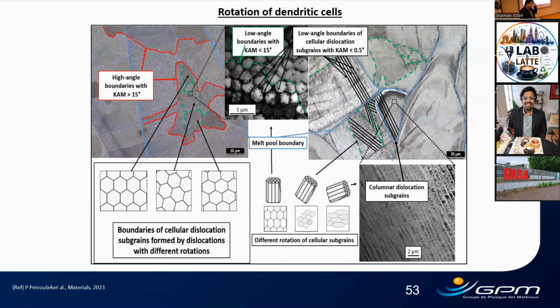So you spoke about microstructure. We did not speak much about defects. Just considering the large range, usually when you look at a range of VEDs and you put that in a map of defects, you make a summarization. You can analyze the density, and people say, oh, it's 99.98, it's so good. And when you look at the tomography, you're scared about what you see. So you were able to control a fully dense material with this very large range of VED. I mean, you should normally have a defect population popping up somewhere. So the X-ray tomography was done only on one volumetric VED sample, 62 joules per millimeter cube.